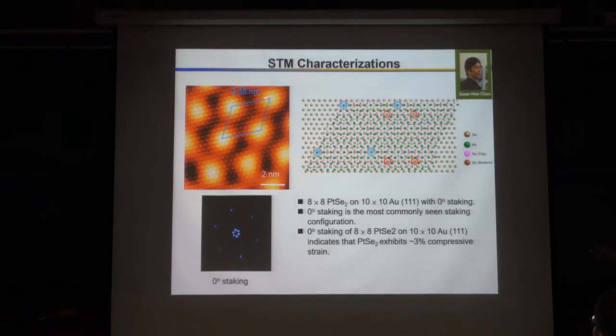And we also use STM. You can also see a Moiré pattern with the same orientation. If you stack PtSe2 on the gold surface, you will find the 8 by 8 structure will almost match with the 10 by 10 gold surface. And in this case, the strain is about 3%. So if you grow the material on a gold surface, there is some strain on the surface. Okay, this is the first part, growth.